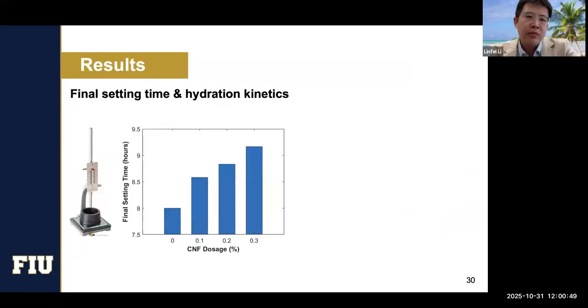And we start measuring. We got a lot of interesting findings, and some of them may be different from what other people find. For final setting time and hydration kinetics, we just use the Vicat needle. Surprisingly, a lot of people talk about the nucleation effect, but our final setting time keeps getting delayed with more and more cellulose nanofiber added into the system.